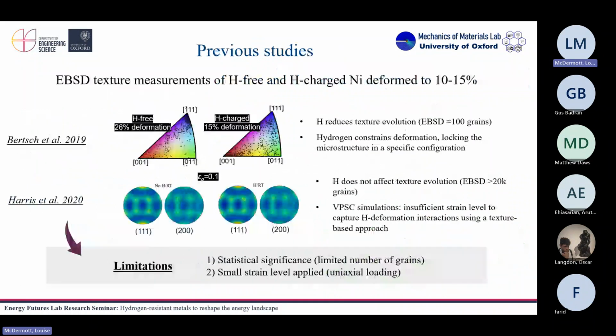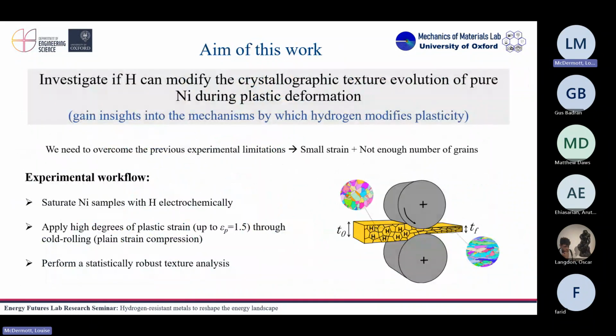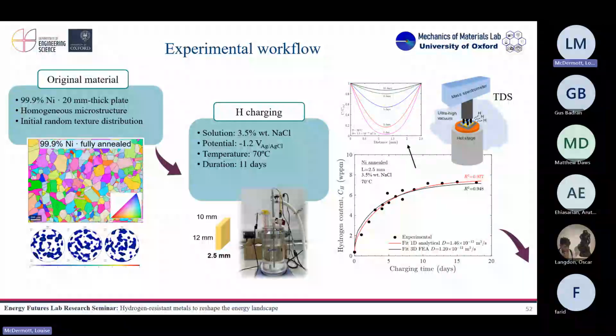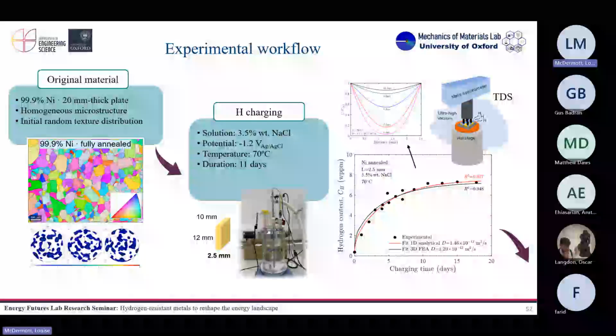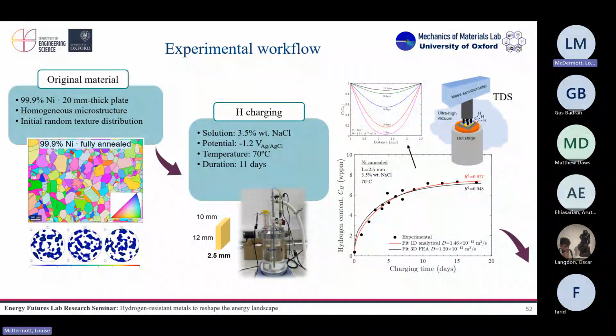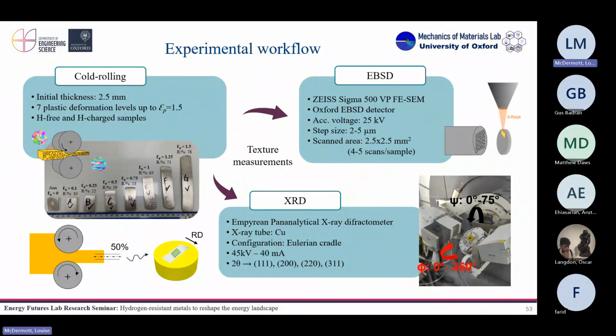Okay, so what we did was to charge a bunch of samples with hydrogen. We tried to introduce as much hydrogen as we could, in this case around 8 ppm, but the number is, let's say, not relevant. On pure nickel, okay, with a random texture. So we don't see preferential orientation of grains here. So we charged the samples with hydrogen and we did cold rolling, okay, because we wanted to introduce as much deformation as we could without breaking the sample.